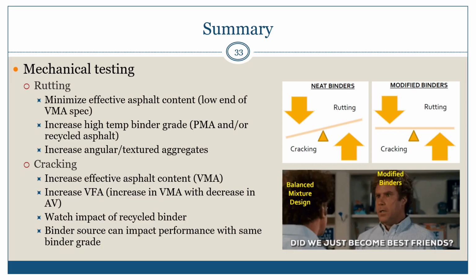To meet the cracking, we want to make sure that we have enough effective binder in there, designed to make sure that we have a good amount of VMA to have that durability. Looking at, from a volumetric perspective, increasing your voids filled with asphalt. Now remember that that's an increase in VMA with a decrease in air voids. That can be handled that way by lowering your air void. Watching the impact of the recycled binder and the source of the recycled binder. And last but not least, binder source can have a significant impact on performance. And quite honestly, when we want to consider all of this together, increasing effective asphalt with the use of a polymer modified binder might be something that could be very quickly implemented and used in a very simplified manner to ensure that we're getting our durability and rutting resistance.